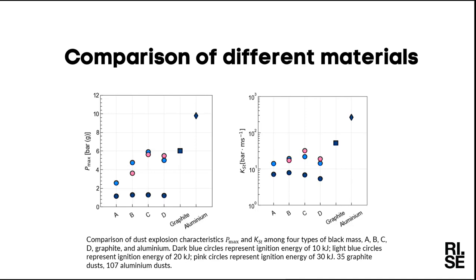And then on the right-hand side, we have the KST for different materials, and KST is the maximum value of the derivative of the pressure curve. So it basically reflects the violence level of the burning process. Again, aluminum has the highest KST, the most violent explosions, followed by graphite, and the lowest is black mass. Here it is a logarithmic scale, so aluminum has very high values in those comparisons.